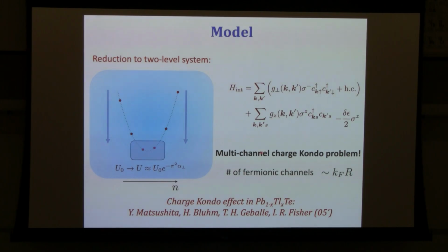It's a multi-channel charge Kondo effect, a charge Kondo problem with a number of fermionic channels, incoming and outgoing channels, interacting with this charge Kondo impurity, that scales like k_F, the Fermi momentum, times R, which is basically the size of the perimeter of this superconducting island. If we think that the size of these puddles is maybe a few nanometers, this number is maybe 10 or 20. So that's the regime we'll be interested in. I won't go into a lot of details. I'll just flash a few results coming from analyzing this model and conclude.